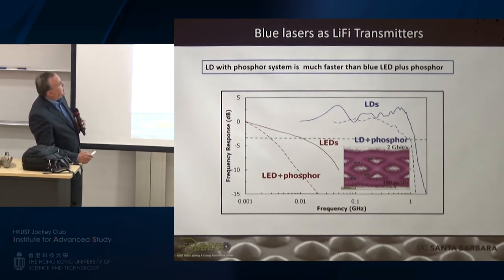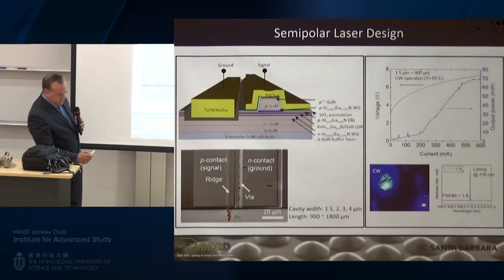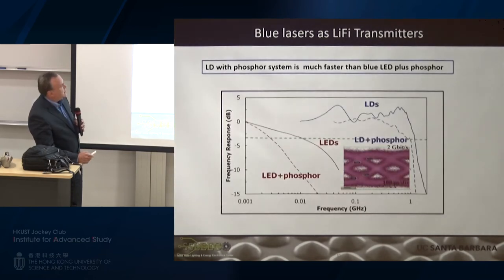LEDs have sped up, lasers have sped up too, but it still shows you one of the main advantages of lasers over LEDs. In comparison to the LED, at least with our laser and LED systems, we were able to get, with a laser with a phosphor on it, over 2 gigabits per second of communication speed without even trying in a free space environment. LEDs early on were about 100 megahertz. I've seen them get out to a gigahertz now,